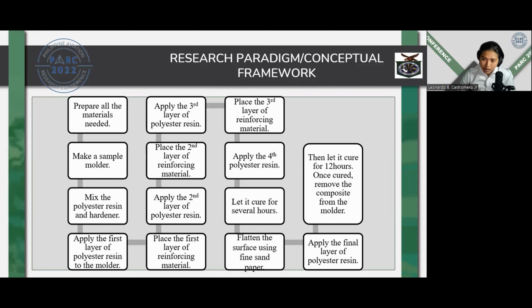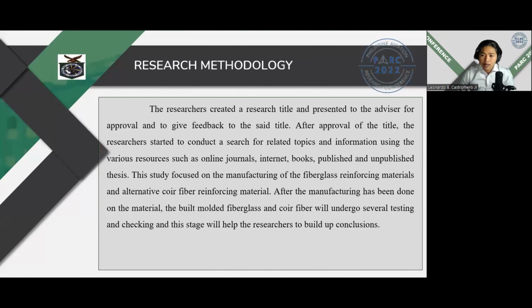Then apply the third layer of polyester resin. Next is to place the third layer of reinforcing material. Then apply the fourth layer of polyester resin. Then let it cure for several hours. Next is to flatten the surface using fine sandpaper. Then apply the final layer of polyester resin. Then let it cure for 12 hours. Once cured, remove the composite from the molder. Research methodology.